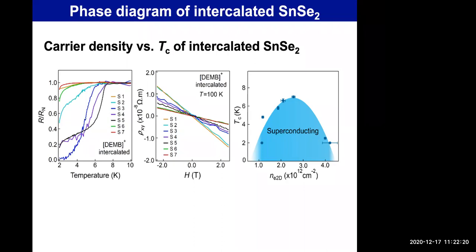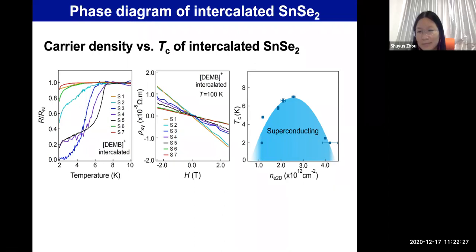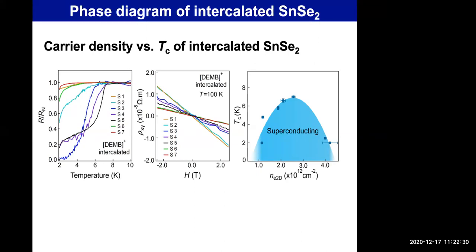I wasn't trying to infer that spin fluctuation theory is actually in charge of superconductivity here. I was just really impressed by the correlation that one can see between the change in the dimensionality of the system and the variation in the superconducting transition temperature, in a fashion which is very similar to the cuprates, but also to some of the heavy fermion compounds. I just wonder what could be the correlation between these very different systems and yet quite similar behavior. And I wouldn't worry so much about the doping dependence of your charge carrier, because the question, of course, is which carriers do participate and which don't. That's another thing, but it was just an observation which I find fascinating.